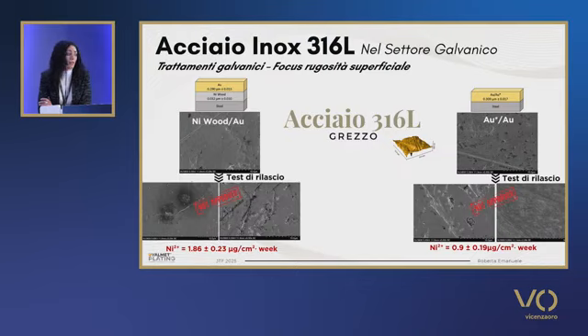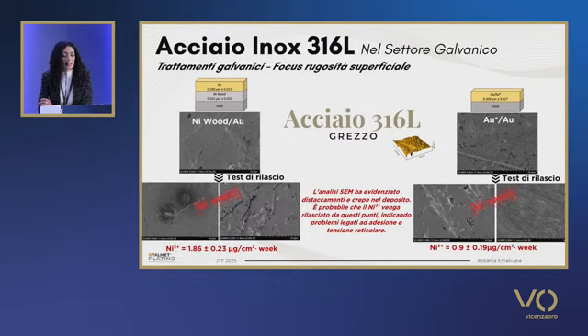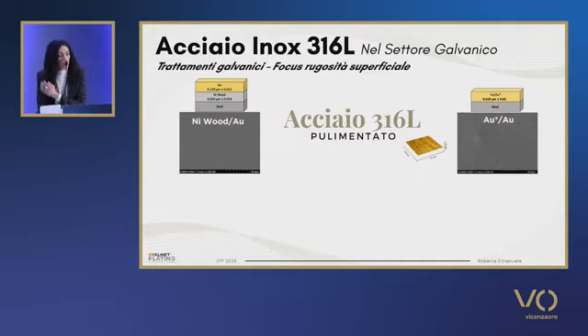So this means that the superficial activation and the removal of the chromium oxide that was necessary for the coating made it more liable to release nickel. In the SEM images, you see that there are many cracks on the surface, so probably nickel is released by these very quick cracks, where there is a problem with adhesion, and that could be due to an excessive roughness of the sample.